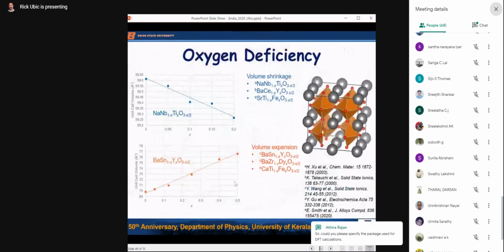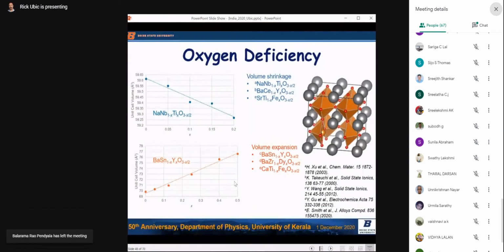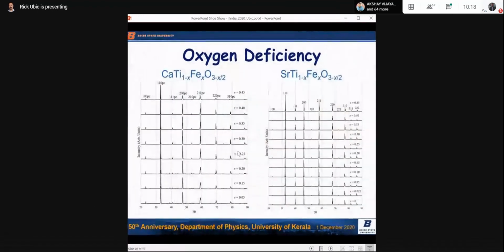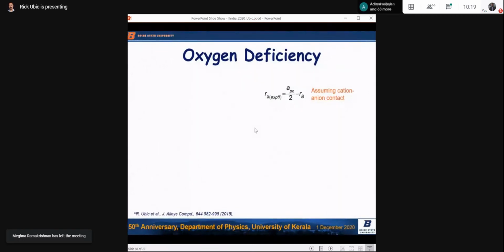Okay, now let's look at oxygen deficiency. The last thing I want to talk about, but it's important. Oxygen vacancies can cause either volume shrinkage or volume expansion, very commonly both ways. We used calcium titanate ferrite and strontium titanate ferrite. We got single-phase materials. In this case, there's a phase change from orthorhombic to tetragonal. These are all tetragonal. But the important thing here is from geometry, this is the same equation we had before, if you remember, many, many slides ago. But now we're solving for Rx instead of Rb.